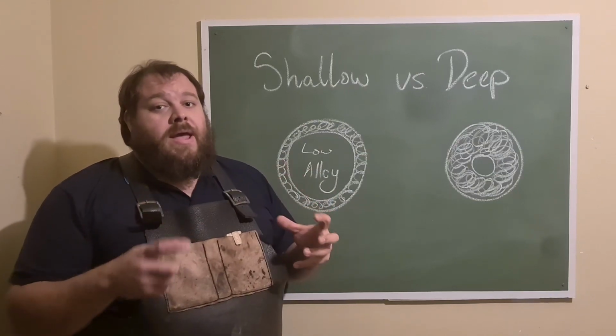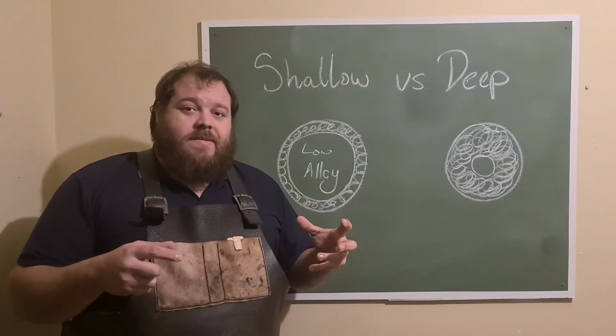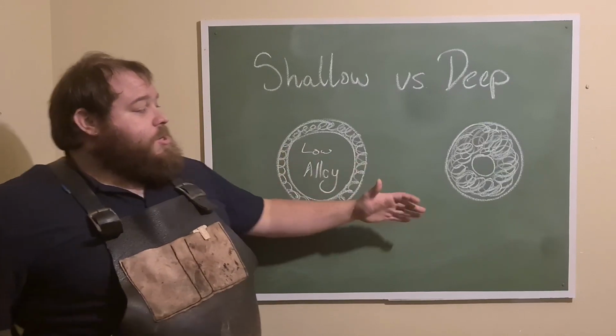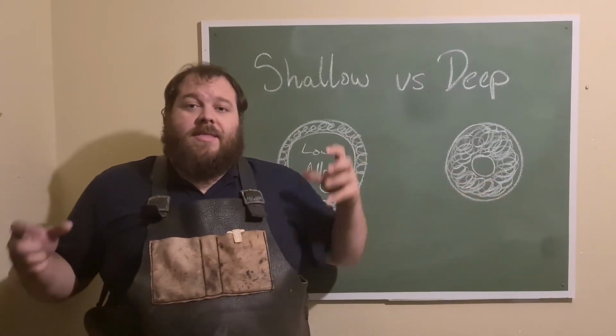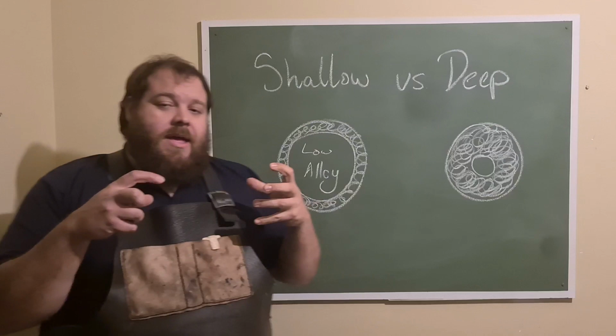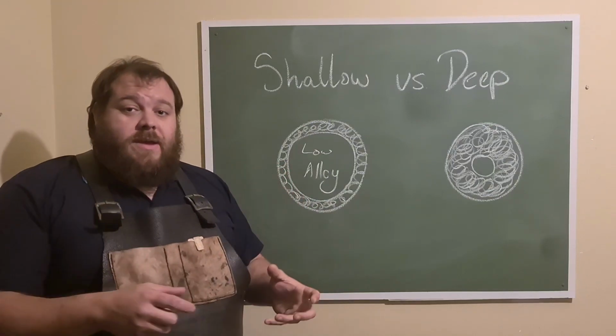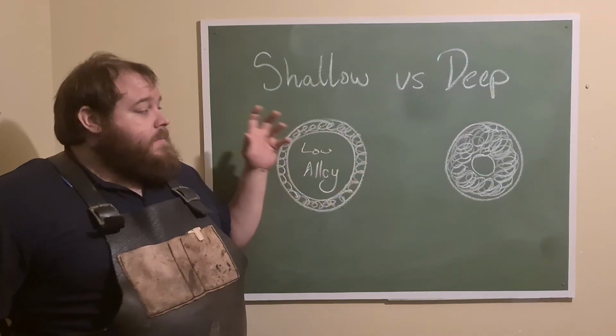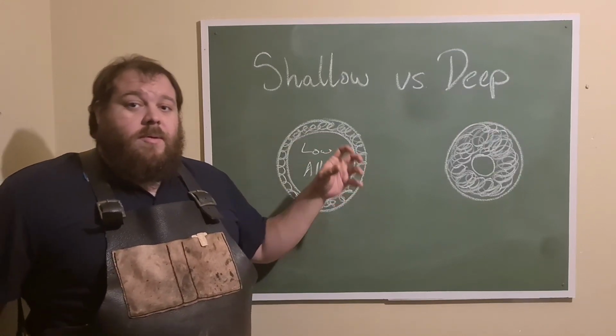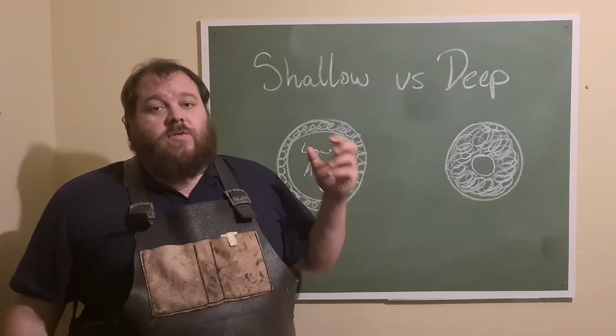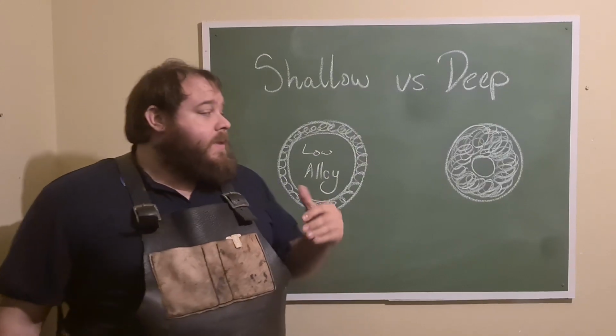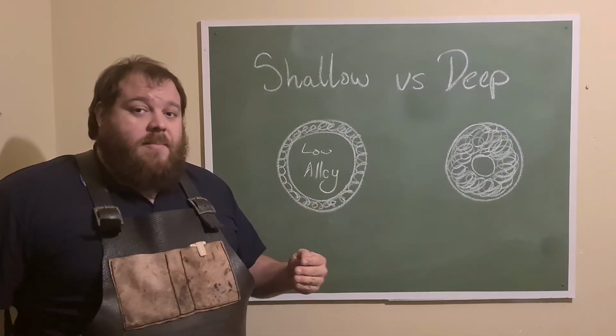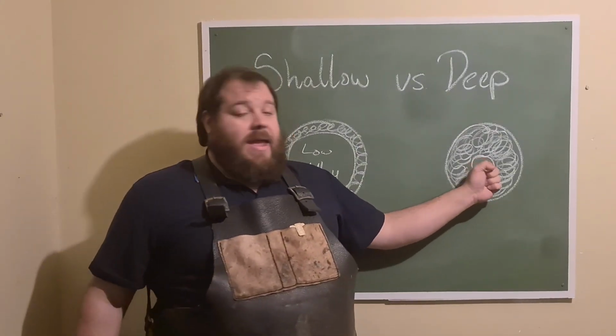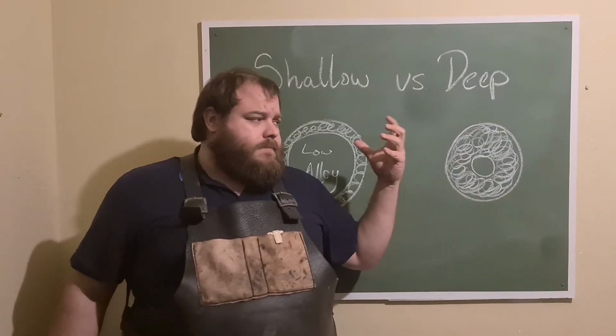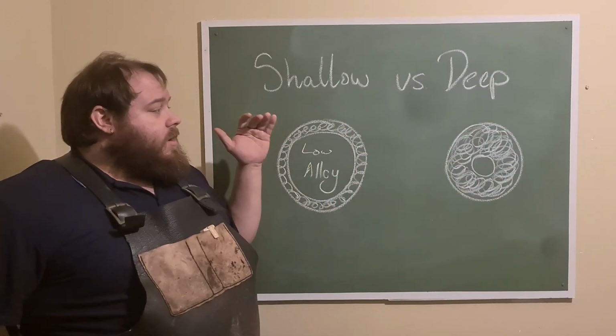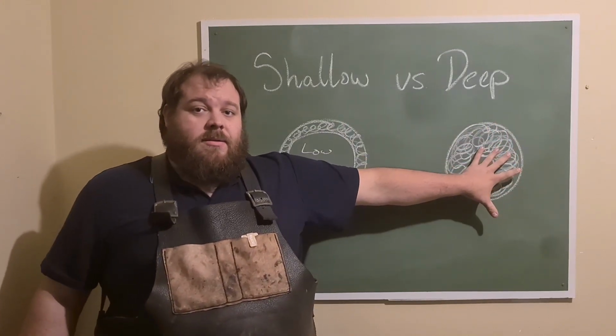As we know, you can burn out carbon if you over-oxidize your steel. With the addition of alloying contents, that carbon then has something else to attach to. And in a conversation I had about hypereutectoid steels in a previous video, we know that that can form carbide. So carbide segregation happens due to high alloy content. That precipitation of carbides can also occur in depth in the material. And so the lower the speed of quench needed, the deeper the hardening.